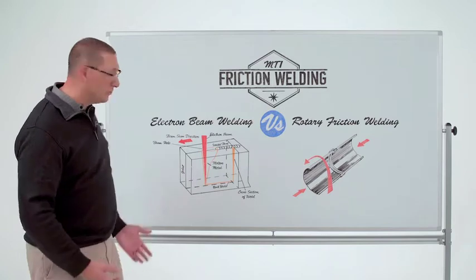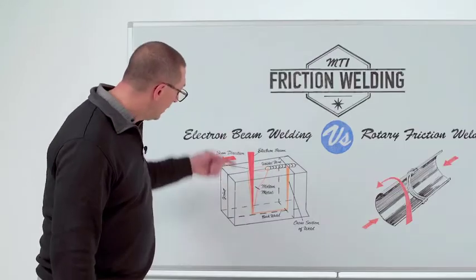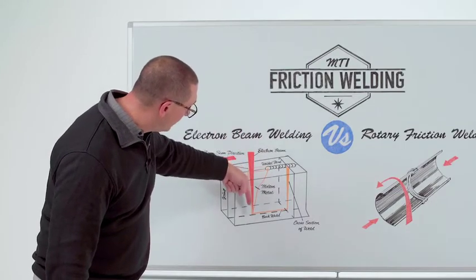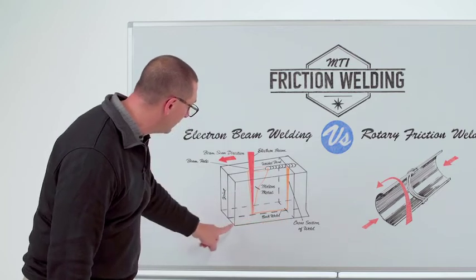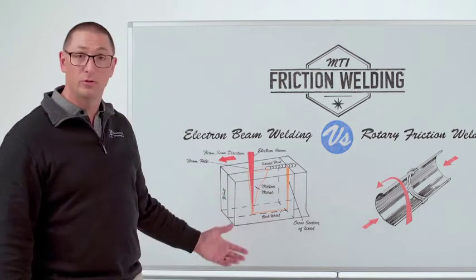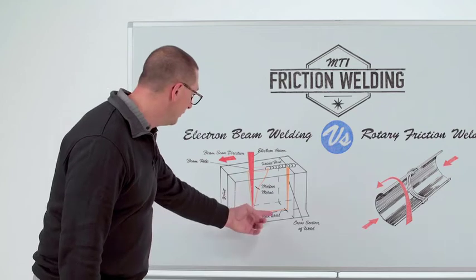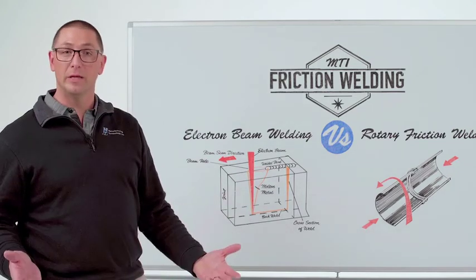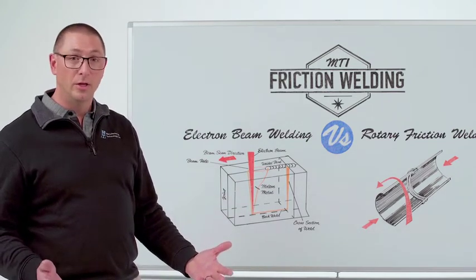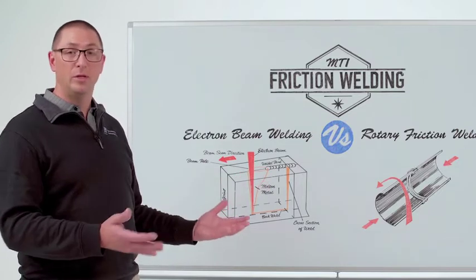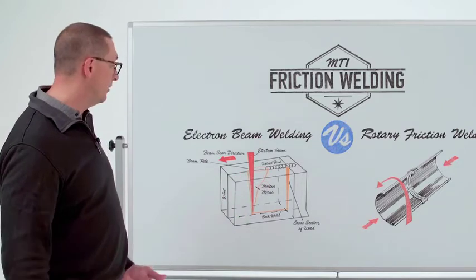You will have to do some post-weld inspection because if the beam doesn't impinge far enough, you could have a defect at the backside of the weld, or if it goes too far, obviously you can leave a defect at the back of the weld. So you'll want to be able to detect that in inspection. You can repair an EB weld, but it decreases the life of the component.